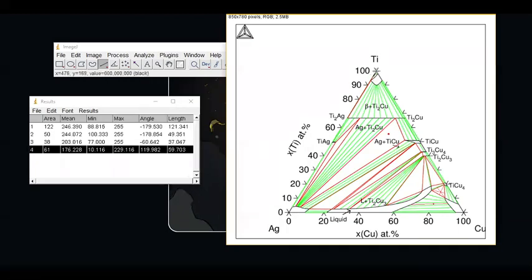This small portion here is the alpha titanium, and therefore this next phase is the beta titanium. Is that clear? Since you don't have much experience yet with different types of systems, you may be confused when it's not explicitly stated what the Greek letters expected for different phases mean. But usually, whatever is most stable at room temperature becomes the alpha. Notice that iron at room temperature is called alpha ferrite, right?